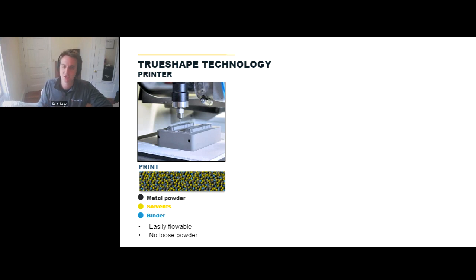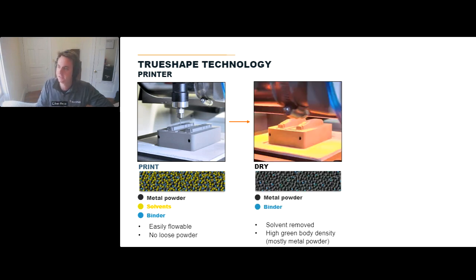In this stage, the material is very flowable. There's no loose metal powder involved because it's all inside of the slurry. And we're just placing this where we want it to go. After we lay down our material, we come through and we dry. This is done just with heat as well as with a fan. And what we're actually doing here is we're removing the solvent out of the material. So we started with that paste, that metal powder, that solvent, and that binder. Now we're going to heat it and remove the solvent.